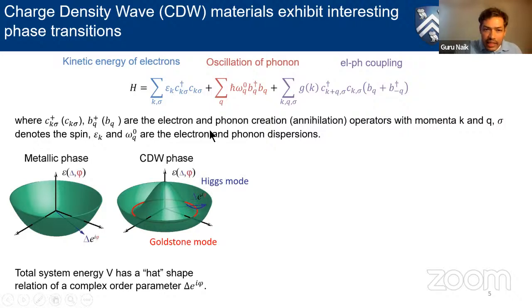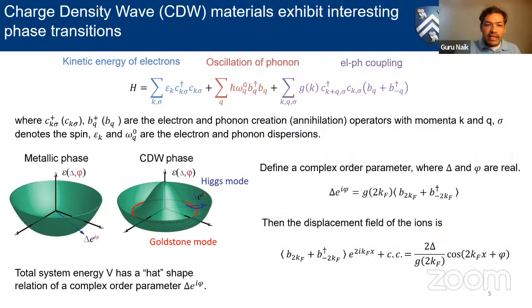But in the case of charge density waves, or generally strong correlation, we see that the energy landscape is no longer the simple cup, but actually a hat shape. Which means there exists a minimum, not at the center, but at some other distance away from the center in this phase space. And that's where the charge density wave phenomenon happens. It's a wave because, of course, it can pick any phase on this circle. They all have the same minimum energy. So you can assign an order parameter because of the energy landscape that shows up.